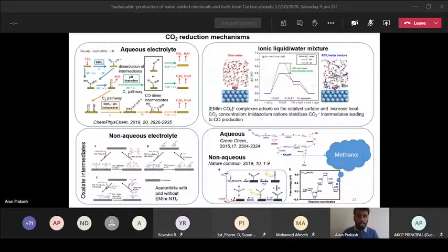In the case of aqueous electrolyte, CO2 will be converted to carbon monoxide first, and then it will proceed through a multiple electron pathway, either the C1 pathway or C2 pathway, and it will form methane or ethylene. And the reason for using the ionic liquid is it will increase your CO2 concentration, because these ionic liquids have imidazolium cations, and these cations can absorb the CO2. Near your electrode, if you coat your electrode with a catalyst containing this ionic liquid, then these catalysts can automatically absorb a lot of CO2 on their surface, and they will increase the local CO2 concentration. And because of that, the imidazolium cation also stabilizes the intermediate, that is the CO2 radical intermediate, and it leads to CO production. So it increases your CO production.